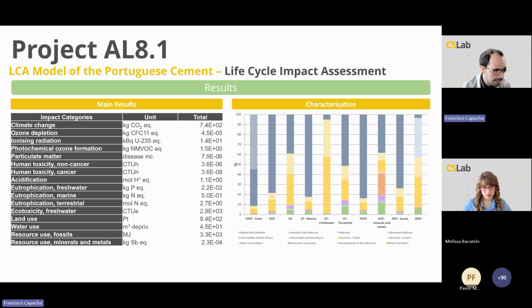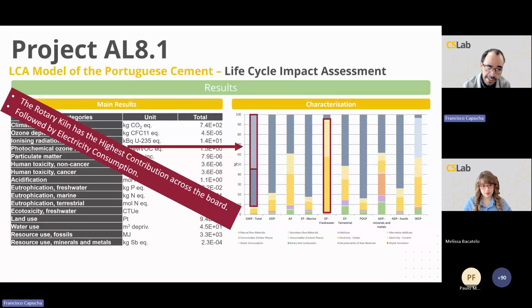After the introduction of the data into the LCA software, this computer model was run to obtain the results which we observe here. The impact assessment was carried out in accordance with the criteria of standard EN 15804 using all available environmental categories, including the optional ones. And we can observe that the rotary kiln activity has the highest impact contribution to the majority of indicators, with special relevance to global warming potential, where it contributes with over 90% of the impacts, which is mainly due to the calcining reactions that occur within it, but also the fuel combustion reactions.